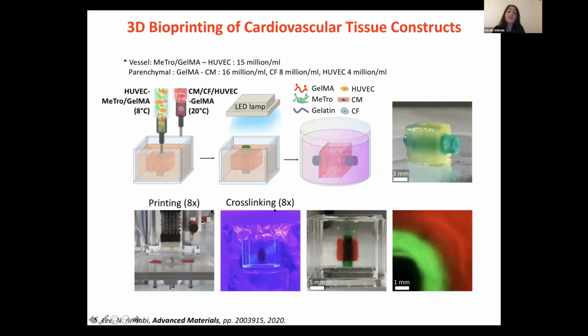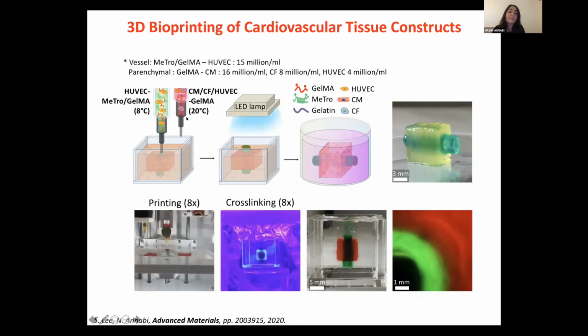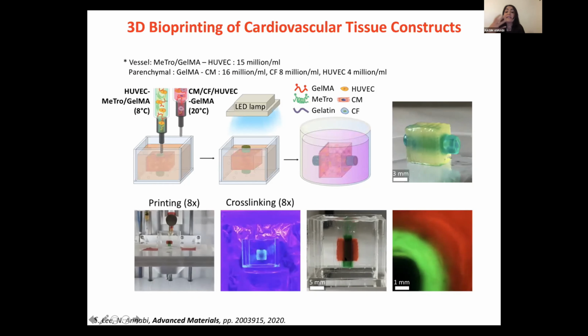Moving from that, we also looked into how we can form more complex structures. For this experiment, again, my students used a two-nozzle printer. One nozzle was loaded with MeTro, laden with HUVEC cells. And for the surrounding matrix, shown by yellow color here, she used gelatin-based bioink loaded with cardiomyocytes and cardiac fibroblasts. And then as we form this structure, you see that it's a continuous process. We can 3D print these structures in a short time, photocrosslink it in the bath, and once we form our structure, we can take it out from the bath and then put it in culture.